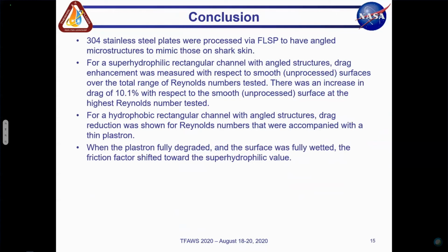So to wrap things up, we use 304 stainless steel plates, process them using femtosecond laser surface processing, or FLSP, to get angled microstructures that mimic those on shark skin. For a super hydrophilic, or wetting, surface in a rectangular channel with these angled microstructures, we measured drag enhancement, or an increase, over the total range of Reynolds numbers tested, with 10% drag enhancement at the highest Reynolds numbers tested. For a hydrophobic channel with angled structures, we're able to get drag reduction for the Reynolds numbers where we did have a plastron present.